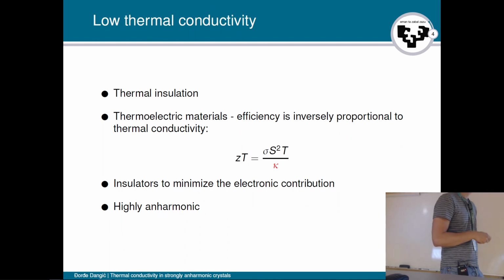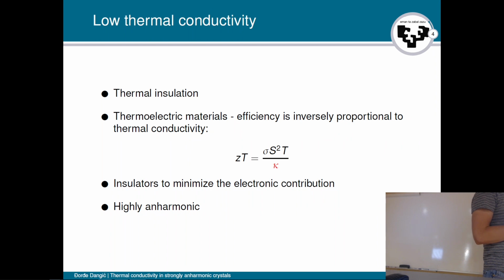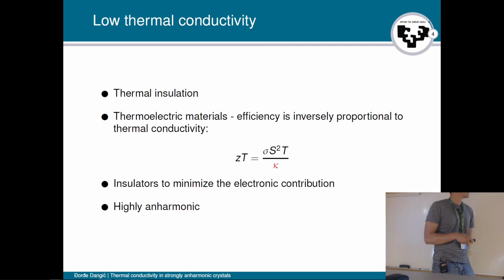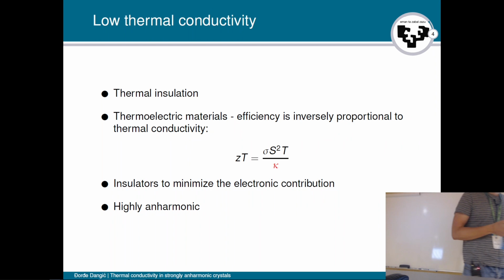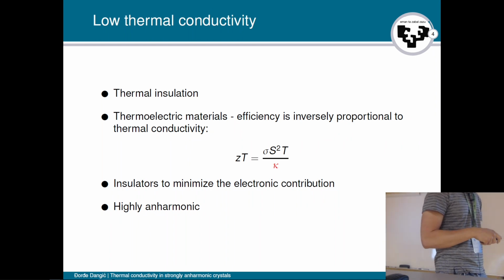So which materials could have low thermal conductivity? Well, the first guess is we need them to be insulators because we want to minimize the electronic part of the thermal conductivity. So what type of insulators will have low lattice thermal conductivity? Well, the best guess is the highly anharmonic materials. Why? Because highly anharmonic materials have a large scattering between phonons, and the large scattering between phonons leads to low phonon mean free paths, and the low phonon mean free paths lead to low lattice thermal conductivity.